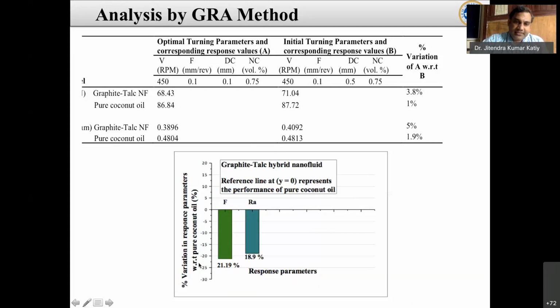So this variation in the response parameter with respect to pure coconut oil, which I observed, is that the feed force is 21.19% improved or reduced in comparison to the pure coconut oil, and surface roughness improves by 18.9%. So those are good results by using this graphite and talc nanoparticle.